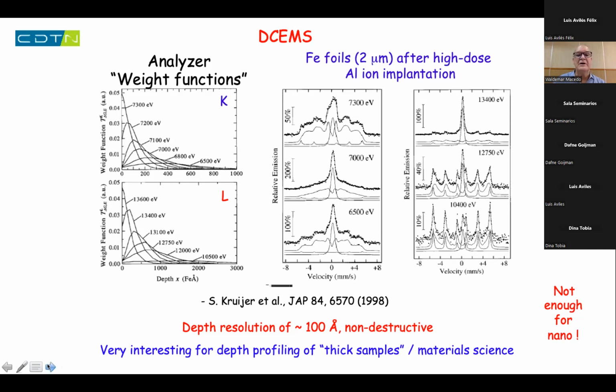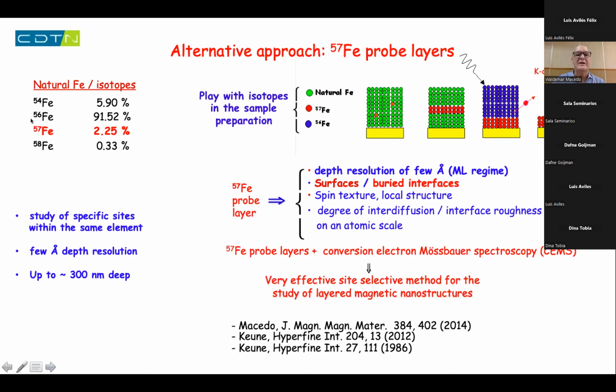If you want to go really nano, one way to do that is to play with the isotopes. That means you know that the Mössbauer isotope in iron is iron 57. It's only 2% of natural iron, okay? And if we can play with these isotopes during the preparation of the samples, you can be very, very depth selective. You can go to the monolayer regime inside the materials, okay, if you are able to play with the isotopes. If you use the iron 57, you are fully Mössbauer atoms, and the iron 56, for example, you don't get any Mössbauer signal from these things, okay? That means using this iron 57 probe layer is a very effective method to investigate layered materials based on iron, for example.